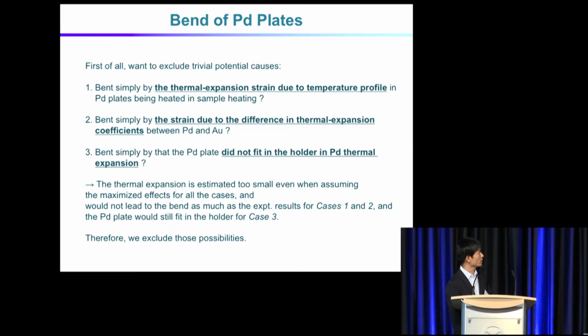And then for the bending observation, we first wanted to exclude very trivial causes. First, the bending might happen due to thermal expansion or strain due to the temperature increase or profile. And also the strain due to the difference in thermal expansion coefficient between the palladium and the gold film. And also, probably this is a stupid possibility, but simply the plate did not fit in our holder when it expands, so it bent. But as we examined all three of those, they could be excluded very easily.